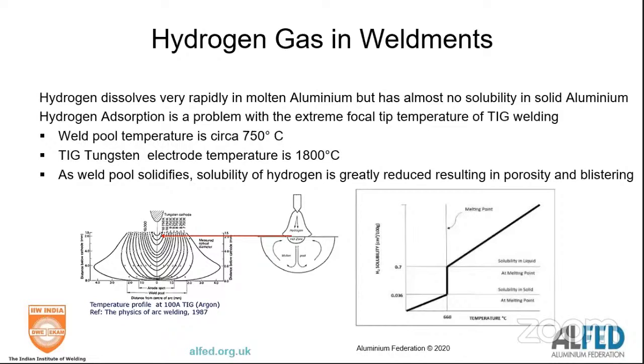Now, hydrogen in aluminium is incredibly soluble. In liquid aluminium it has very, very high solubility. One of the problems with TIG welding is the high temperatures. At the tip of the TIG electrode, you're at temperatures of 1800 degrees C, and the solubility of hydrogen is incredible. But at room temperature, hydrogen has virtually no solubility in aluminium.